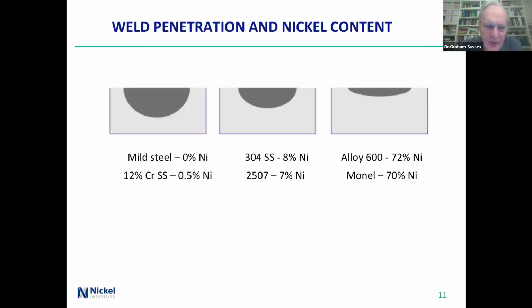Okay, so let's talk about the fact that we're actually going to be doing welding on these alloys. This is the sort of penetration that you get if you're used to doing mild steel. If you're using 12 chrome steels or stainlesses, that's the sort of penetration you'd actually get. If you're looking at 304 or a super duplex, 7 or 8% nickel. And if you're looking at a Monel, that's a 400 or K500, then it's about 70% nickel, and that's about how far it would go through proportionately. So it's not that anything's gone wrong with the way the welding is going, it's just an inherent factor in terms of that. And those of you who use high nickel alloys will absolutely recognize this.